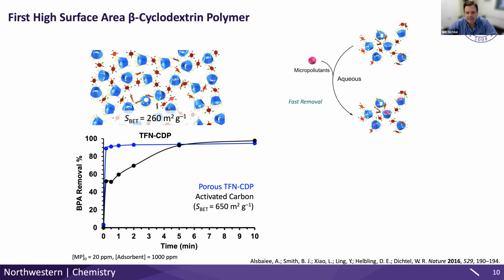And this was even faster than several activated carbons. This is kind of that same experiment. Even though our material has a lower surface area than the activated carbon we were benchmarking in this experiment, the surface area works a little differently here, because the activated carbon uses the surface itself to bind pollutants. So the higher the surface area, the higher the capacity generally of the activated carbon. Here, as long as the surface area is sufficient to make those cups accessible, we can get this really, really fast binding.